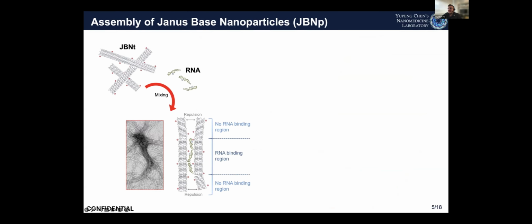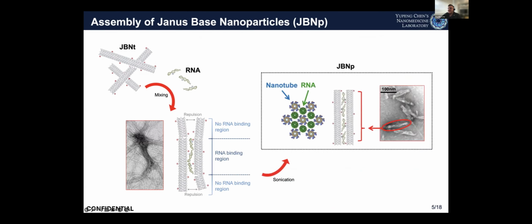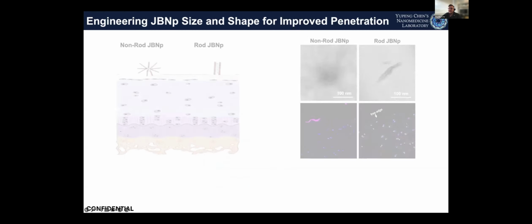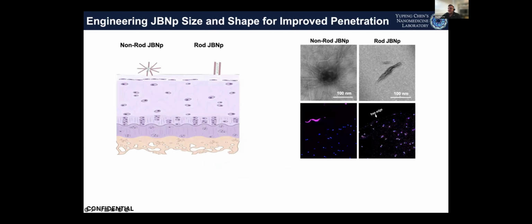Then, we sonicate the materials, where the power of sonication is strong enough to chop up the nanotubes at the non-binding regions, but weak enough to leave the RNA binding regions intact. This leaves us with RNA that's tightly bound between nanotube bundles and a nanoparticle that stands at around 100 nanometers long and 5 to 20 nanometers wide. One of the key advantages of JBNP is that we can engineer its size and shape for enhanced penetration into the cartilage.